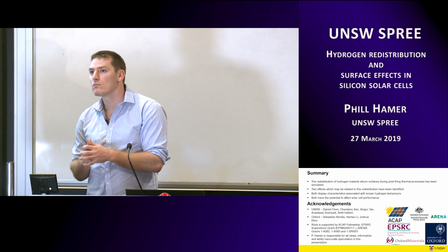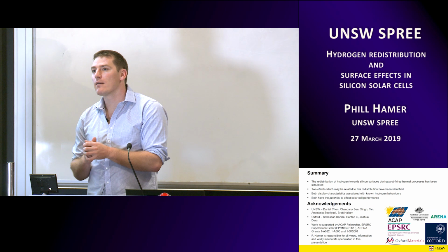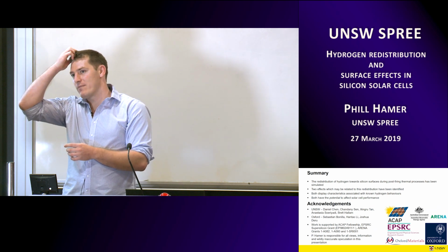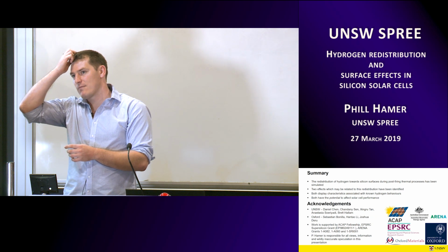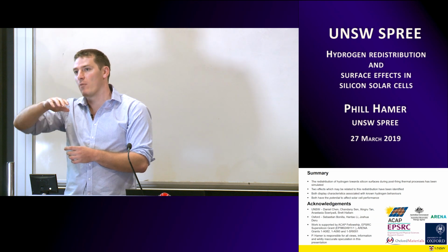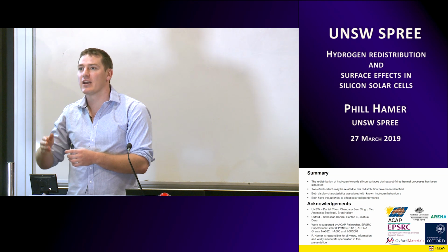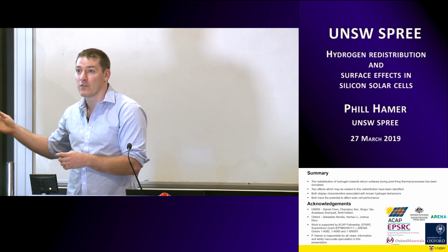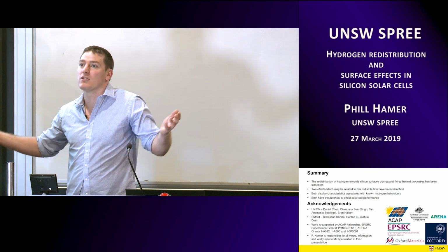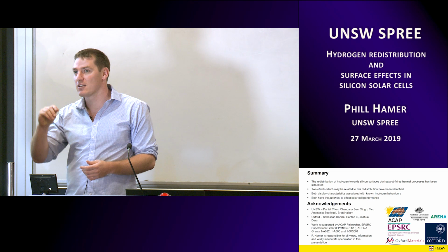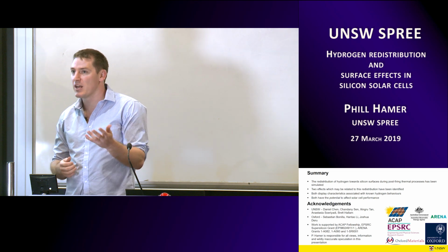Yeah, I think it's just very easy to see it. Just from any given sample, you will introduce heaps of hydrogen, and you can easily push it away. It's just a matter of comparing what you've modeled with that behavior. We can do it with specific structures. Again, the problem is with the very high doping at the surface. I mean, we can deactivate 10^18 phosphorus right near the surface. Doesn't make any difference because we've got 10^21 phosphorus active. So it's making sure we have a significant enough effect to be visible using that method, which has been a challenge for some of the phosphorus deactivation.